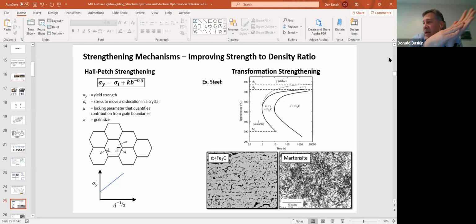There's a very old, storied, famous company that makes tubing for bicycle frames called Columbus, and they're in Italy. I think they have really pushed the boundaries of steel technology for bicycle frames. One of their most modern alloy developments contains a lot of niobium. And this is exactly what they're doing. They're decreasing grain size by adding niobium. The niobium changes the energy associated with the grain boundary, so it becomes thermodynamically more favorable for the material to have a small grain size. Very, very potent effect.